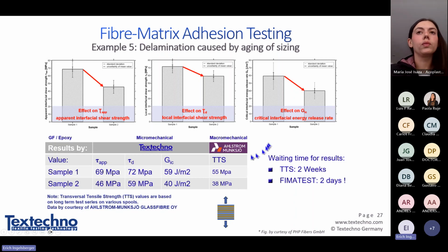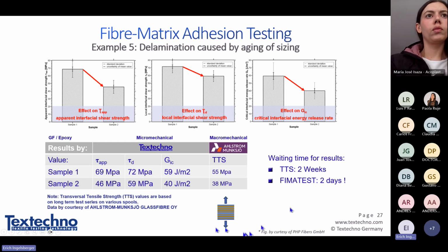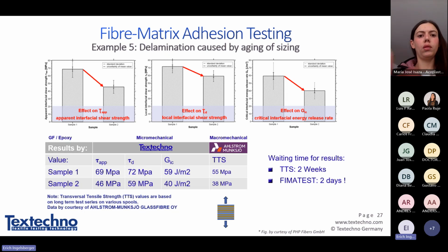Interestingly, the company Ahlström already does some macromechanical testing. This is a so-called transversal tensile strength test. Here you can see a model of the test specimen to check if the quality of the final composite is good. The disadvantage of this test is it will take about 2 weeks before you get results. With our system, you get results in two days already. There is some time required to cure or harden the matrix precisely according to the producer's parameters and regulations.